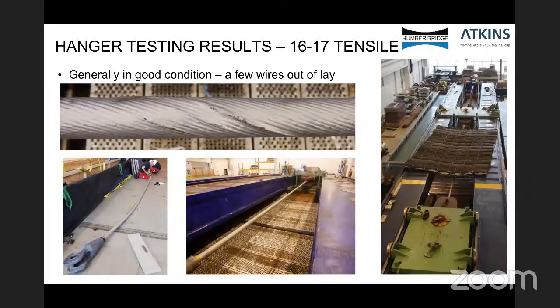This shows the full-scale testing equipment that was carried out. This is for hanger 16-17. It's been set up for the ultimate tensile strength test, which is the first test that we carried out. You can see there the condition of the wires. The hanger, although in pretty good condition, you can see a few wires out of lay and potentially painted over throughout its design life. So this is one of the worst condition hangers.